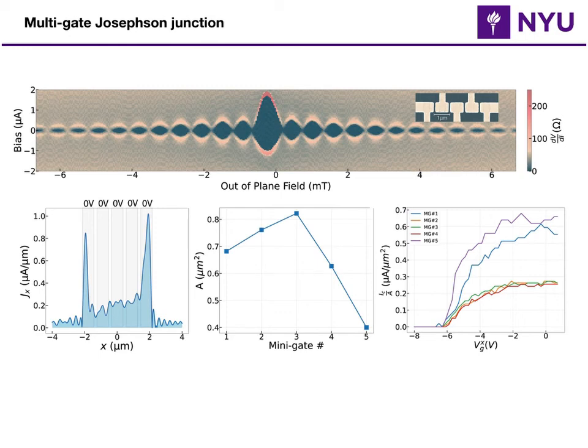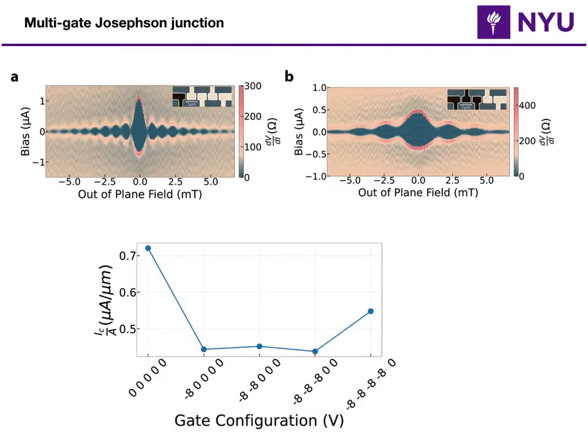So if I only change the gate voltage of mini gate 1, I basically get the blue curve. So I have some supercurrent divided by the area, and then it depletes, right? Something very surprising is that mini gates 1 and 5, which are the end mini gates, have a much higher IC divided by A compared to the 3 middle ones, which are almost identical within the noise of the data. This is interesting, and I will come back to this, but in an ideal case, all 5 graphs should have collapsed into this one graph, right? If the current was uniform all across the junction.